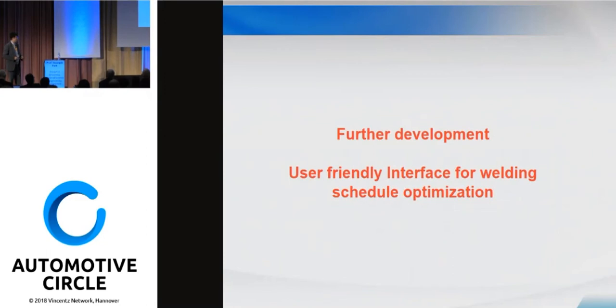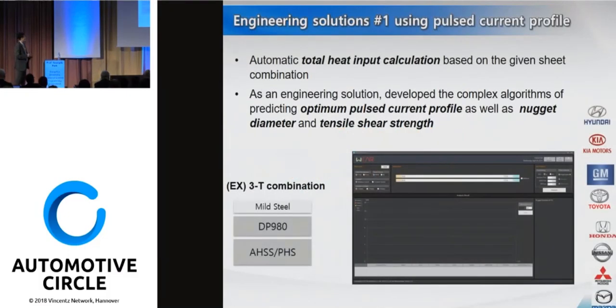So here's the further development. We tried to reveal some of the mechanism and make some calculations, but the automotive companies were still not quite satisfied with this kind of algorithm. So we made a user-friendly interface for welding schedule optimization. It gives an automatic total heat input calculation based on the given sheet combination, and as an engineering solution, we predict the optimum pulsed current profile as well as the nugget diameter and tensile shear strength.